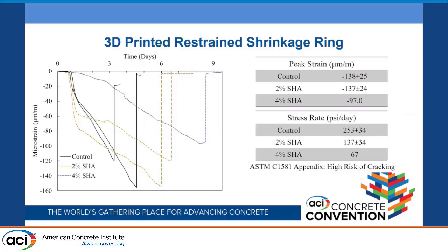After that, we then looked at some secondary parameters, specifically the peak strain and the stress rate of our 3D printed mixtures in the restrained shrinkage ring test setup. Again, we saw high risk—our stress rate was relatively high for all of these samples. Above 50 is generally considered high. As well as, again, we were starting to see a little bit of leveling off where our 0 and 2%, or control and 2% self-healing agent, were comparable, but our 4% was still decreased.